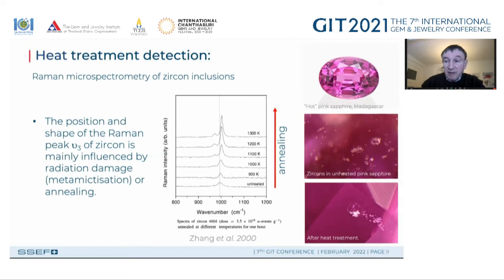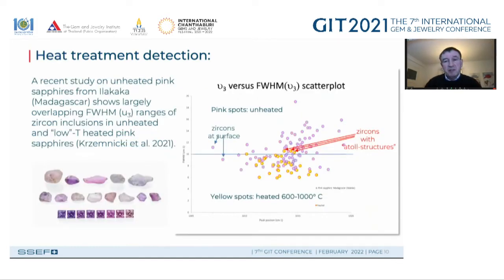However, and this is the next slide, it is more challenging when we talk about the low temperature heat treatment. What you see in this plot is the peak position on the horizontal axis versus the full width half maximum of the main Raman peak of zircon inclusions in corundum. The pink spots represent unheated stones. And you see some of these samples in the color range from pink to purple from Ilakaka in Madagascar. You see a large variation of these peak sizes.